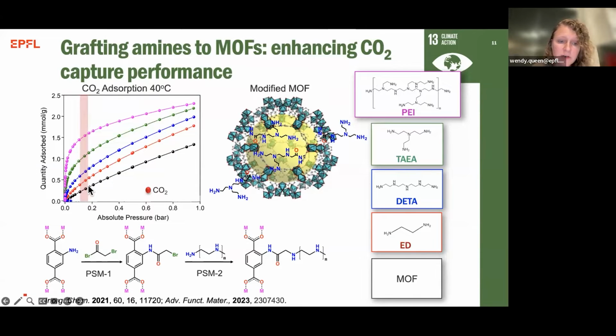So here in black, you can see the parent MOF. You can see here in this low pressure regime, this is the approximate partial pressure of CO2 in post-combustion flue gas. When we modify it with our first amine, we see a slight increase in capacity. And then you can see that as we modify it with more and more primary amines, we see significant improvements up to about 1.5 millimoles per gram for this material.